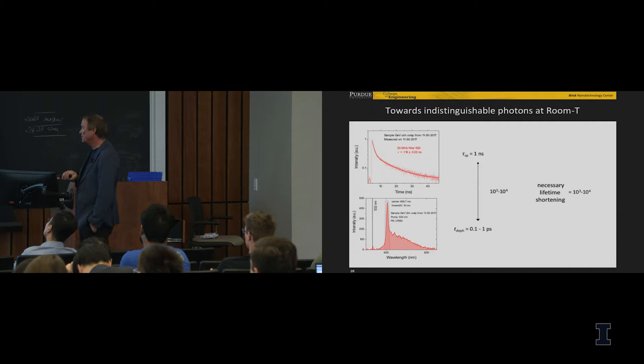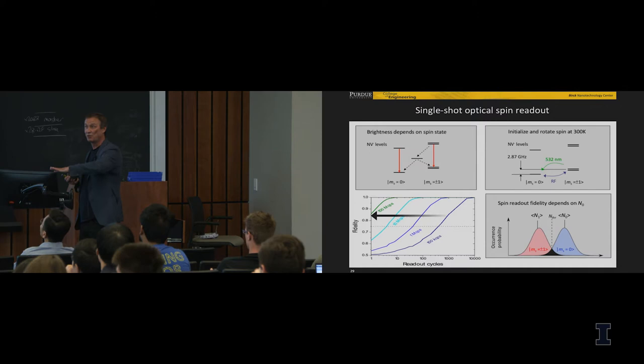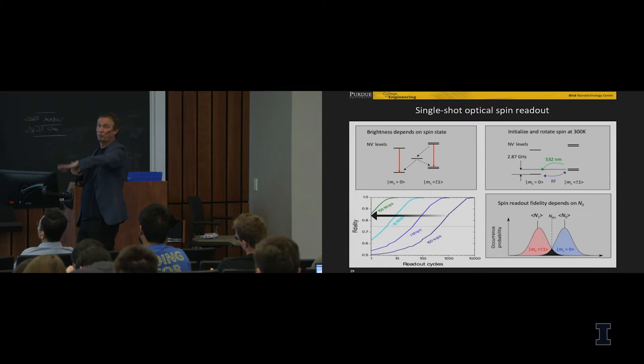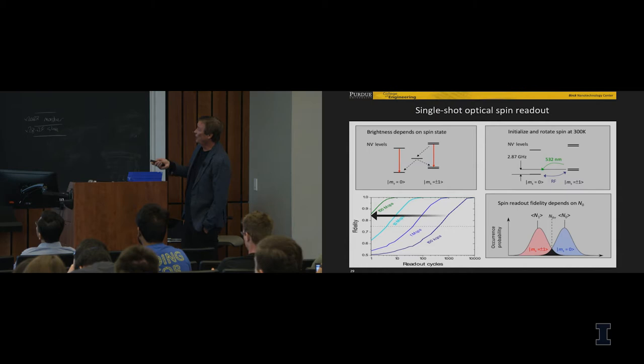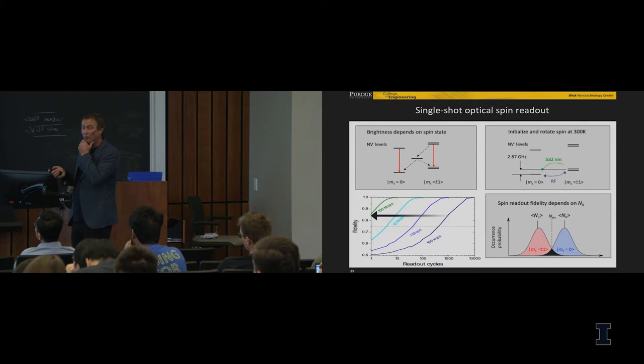Another important application I already mentioned is that nitrogen vacancy also has a spin degree of freedom, which could be used for memory to record a bit, like one or zero. That's the spin degree of freedom, which you could initiate by microwave radiation, switching from 0 to 1 by sending these pi/2 pulses, for example. And you could read it optically, which is very important. But to read it optically, you have to do it fast, because when you pump it too long with optics, eventually everything would go to the state S equals 0. Because of this non-radiative channel, there is an asymmetry in fluorescence for the state with spin projection 1 and the state with spin projection S equals 0.